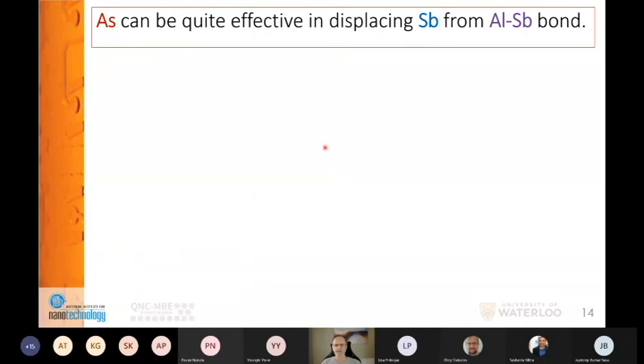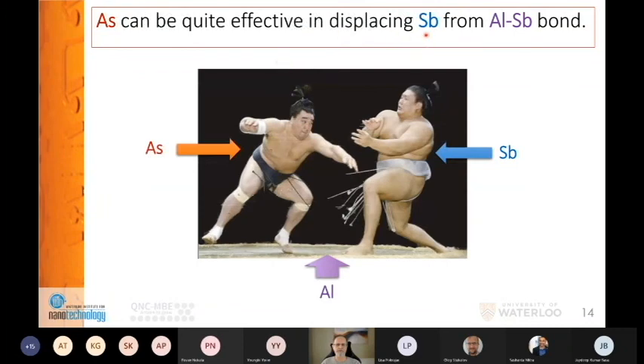And this is because the arsenic is competing in displacing antimony from the aluminium antimonide bond. And it's a pretty complex battle there, very much dependent on the growth conditions and how you do things. So we don't rely really on the absolute values. We just take from this experiment the information that we have a constant flux of bypassing arsenic, the shutter, and we have some initial extra flux during the first monolayer.